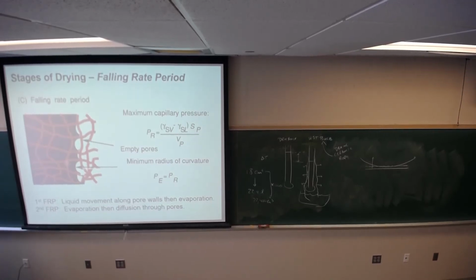Okay. Now he was really interested in drying of gels, and gels represent for us a rather specific special problem because you have extremely high surface area particles and you have a lot of water in the system, and that requires a huge amount of rearrangement of particles. And if you do that in such a manner that it's done too quickly, those particles do not have time to rearrange. The other thing that we have found is that by increasing the ionic strength, those particles will coagulate at the secondary minimum, and then they're able to rearrange each other more easily.